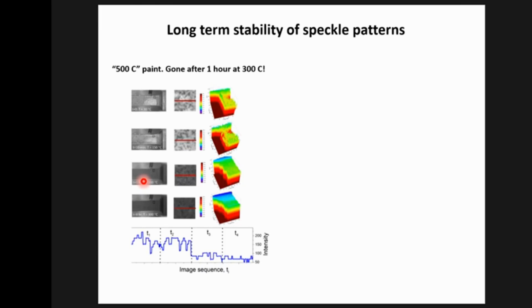So we had to learn, this is all learned the hard way, that so-called high temperature paints don't really last very long. This 500 degree C paint was gone after 1 hour at 300. That is, if you look at the correlation, it's pretty good over here and then gone by the time you get there. So for creep experiments, you really need very long-term stability. A lot of DIC, even at high temperatures, is done with fracture toughness or stress strain curves. So if you have a strain rate of 10 to the minus 3, it doesn't take you very long to do the experiment. It takes you longer to heat the sample up. But if you're doing a creep test for hours, then you need much better stability.